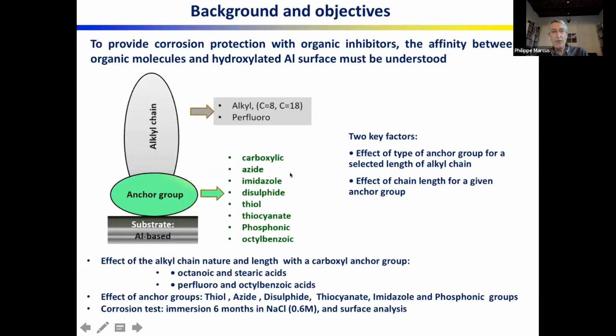So what is the aim of this approach? Well, this is shown here in the background. If we want to provide corrosion protection with organic inhibitors, we need to look at the affinity of organic molecules with the surface, which is, in the case of aluminum, a hydroxylated aluminum surface. So what do we want to understand? We want to disentangle the role of the anchor group on the corrosion inhibition and the role of the chain. So what we did here is we were looking at these two key factors: the effect of the type of anchor group for a given length of alkyl chain, or the effect of the chain length for a given anchor group, because both this anchoring group and the length of the chains are important.